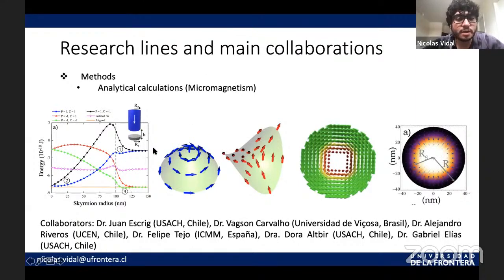For instance, we are able to compute the interaction between nanoparticles with some magnetic configurations. Specifically here, we compute the magnetostatic interaction between a field polarized magnetic tip, a cylindrical magnetic tip, with a magnetic dot which can host a given specific magnetic configuration. We focused on a Skyrmion configuration.